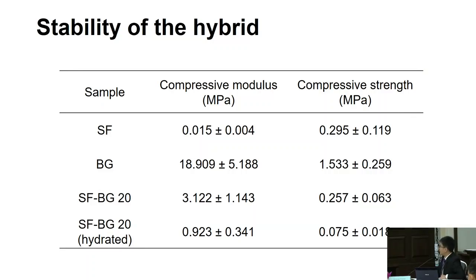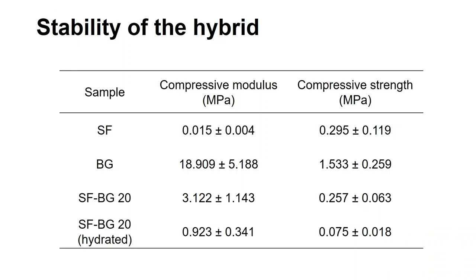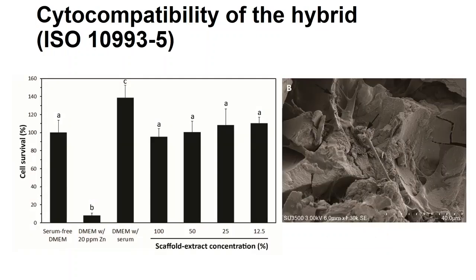And also we tested the mechanical property of the SF scaffold, SF alone, bioactive glass alone, and the hybrid. The hybrid exhibited a mechanical property in between bioactive glass and silk fibroin. And this value is actually getting very close to the lower boundary of the cancellous bone. So we quite like that.